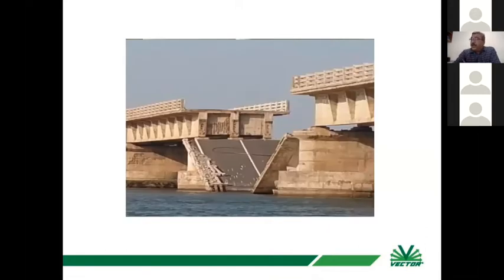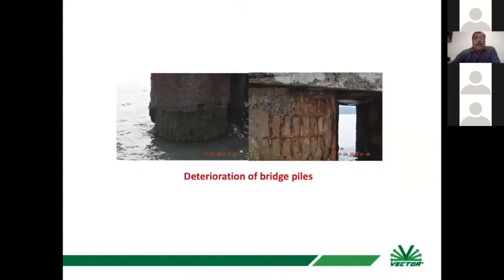And a collapse of a bridge, a typical structural failure of a bridge from the middle of the span because of failure of PT strands, which are a highly neglected item in the entire bridge structure nowadays. One needs to take care of corrosion of PT strands, because they take the majority of the load, and when they corrode and break, this can happen. We are supposed to protect this bridge, but because of formalities and bureaucracy, before we start, it fails. This is the condition of the pile of one of the bridges, which is hardly 10 to 12 years old.